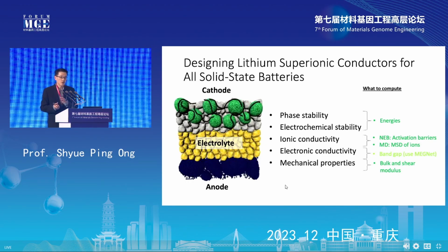We are interested in the phase stability, the electrochemical stability, the ionic conductivity, the electronic conductivity, and the mechanical properties, okay? Now, as it turns out, most of these properties you can actually get from just having knowledge of the potential energy surface, okay? So all these things in green, you can get just from an M3GNet calculation. For the electronic conductivity, you can estimate it using, for example, a band gap model.